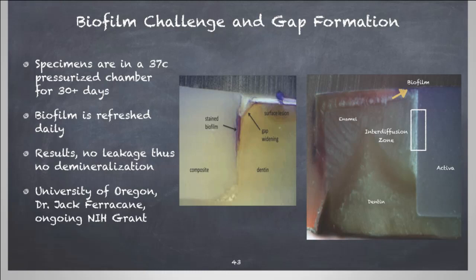So the image on the right is showing Activa after the same thing has been done on every composite in dentistry, showing that the biofilm still forms onto the surface, but not very well. And a recent study that Dr. Ferracane published at the IDR showed that the ability of Activa to retain biofilm is about the same as bioglass. So it's not very well. It can be easily removed. Whereas with dental composites, biofilm attaches very significantly and is difficult to remove, as many of you know.